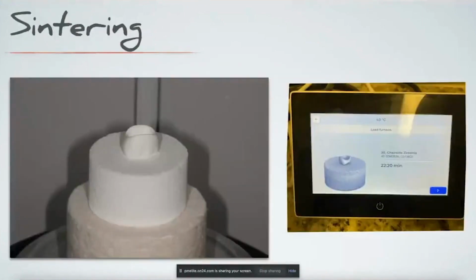Once it's sintering, it sinters on the occlusal side down. And there's two reasons for this. One, we don't want anything of the surface dragging. We also don't want anything impeding that shrinking process that's going to happen. So as you place it here, this is the Speedfire oven from Dentsply Sirona, very fast firing time for zirconia, something that used to take hours, 6-7 hours sometimes in some furnaces. We have it down now to like 20 minutes.